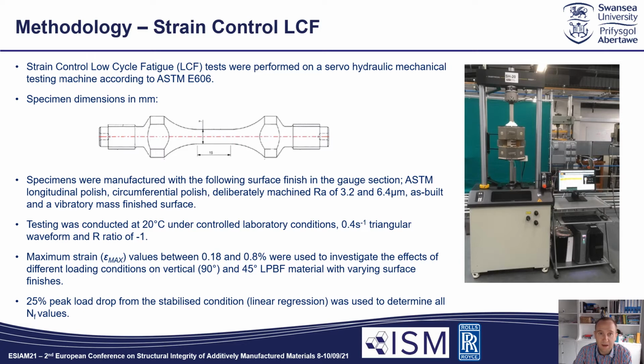All tests were conducted at ambient room temperature under controlled laboratory conditions, and a strain rate of 0.4 and an R ratio of -1 was used throughout. A series of maximum applied strain values were used to generate full SN curve responses across the different build orientations and surface finishes, and failure was deemed to have occurred after a 25% drop in the peak load had been surpassed.